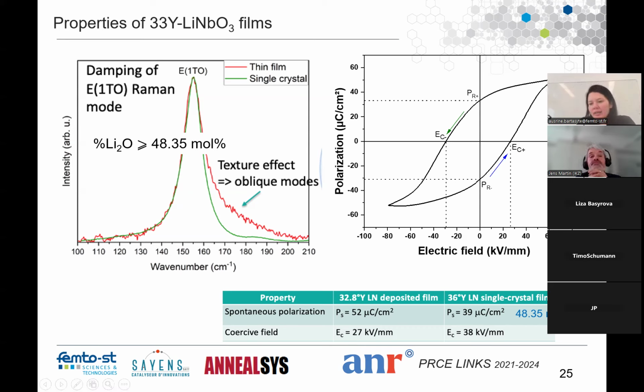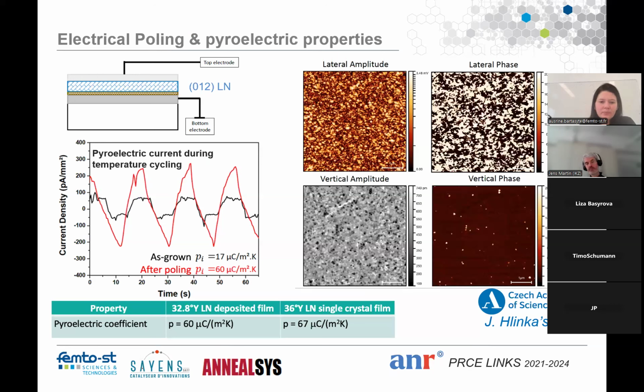And then I have to analyze the broadening of the modes with respect to the defects. It becomes very complicated. But anyway, if I compare to the single crystal mode, probably my film contains more lithium than the single crystal, than the congruent composition. So here we see the ferroelectric hysteresis measured for films. We had a slightly smaller coercive field than a congruent single crystal film, but this is probably because we have more lithium. Again, polarization was slightly higher than expected.